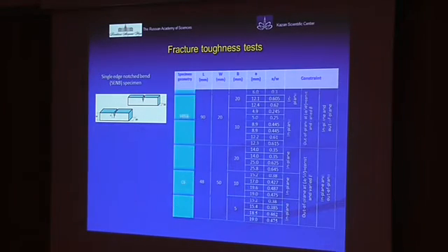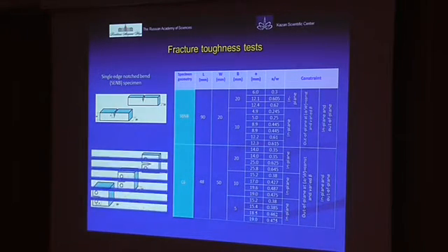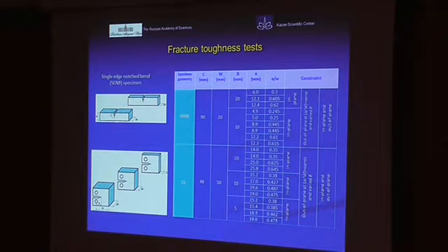First of all, calibration of the plastic stress intensity factor was given by describing the fracture toughness behavior of structural steel. We tested the classical experimental fracture mechanics specimens, bending specimens and compact specimens. In these specimens the range of dimensionless crack length was varied, and the specimen thickness was changed.